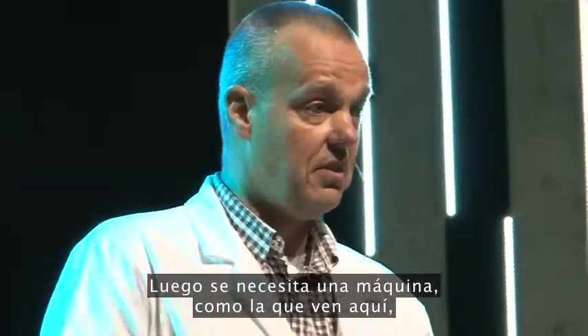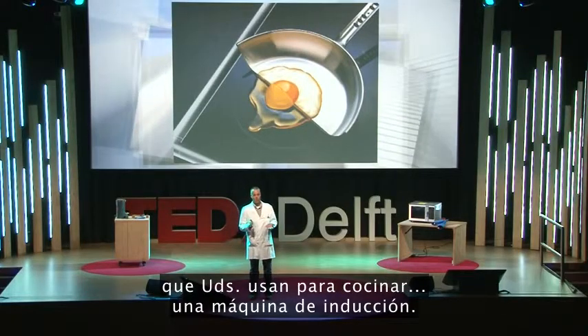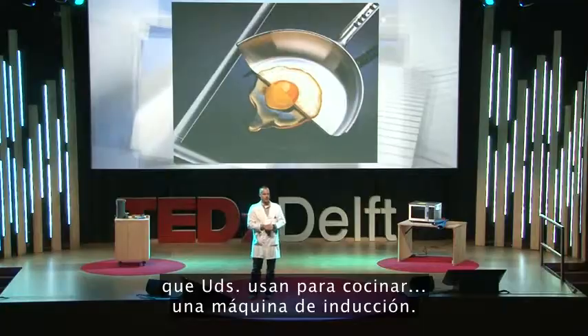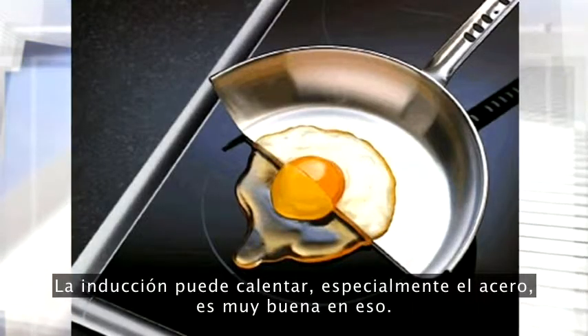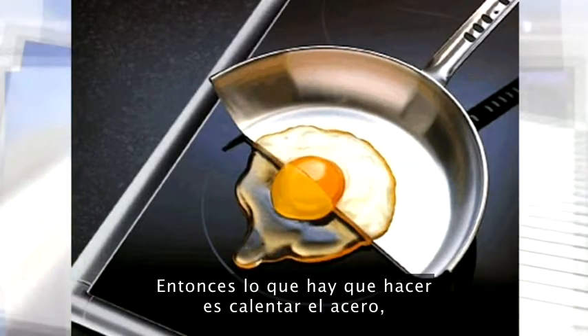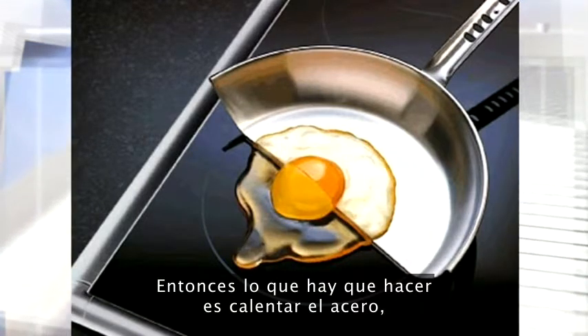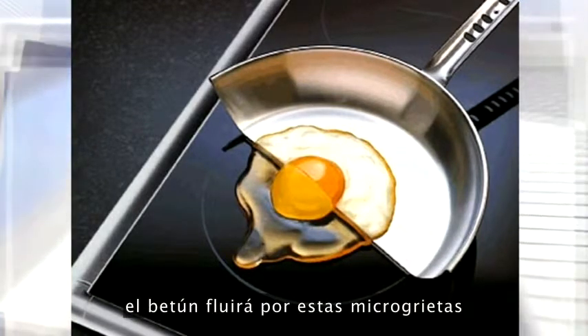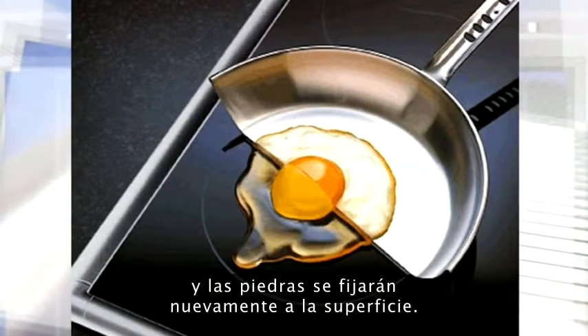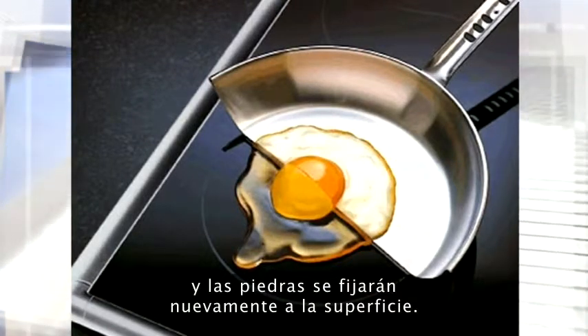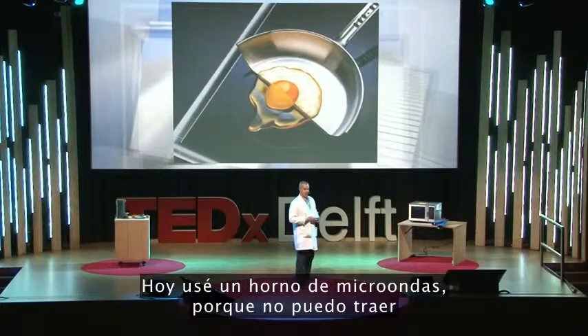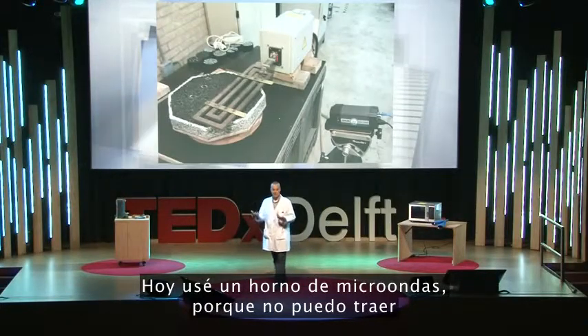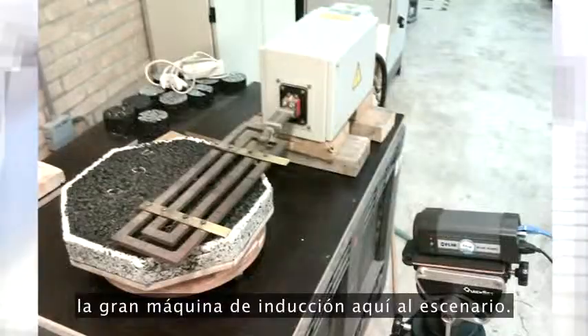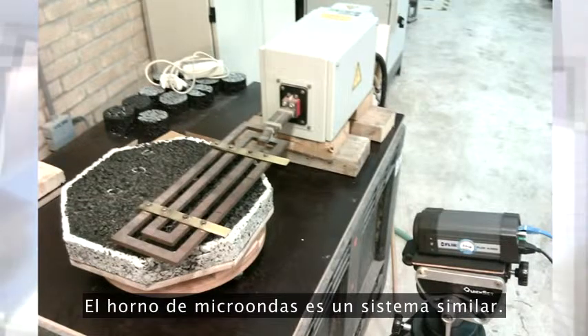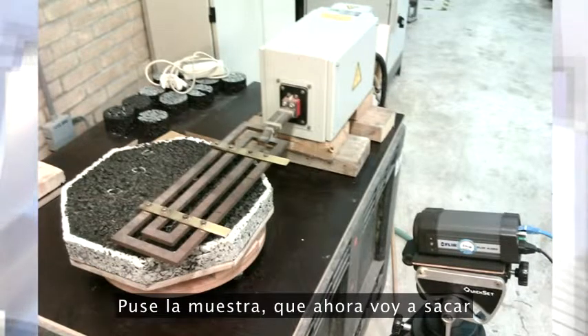Then you need a machine like you see here that you can use for cooking. An induction machine. Induction can heat, especially steel, it's very good in that. Then what you do is you heat up the steel, you melt the bitumen, and the bitumen will flow into these micro cracks and the stones are again fixed to the surface. Today I use a microwave because I cannot take the big induction machine here on the stage, so a microwave is a similar system. So I put the specimen in, which I'm now going to take out to see what happened.